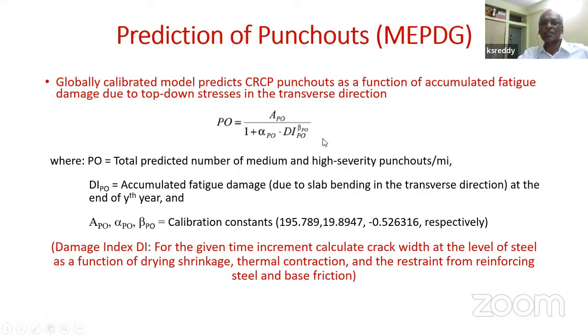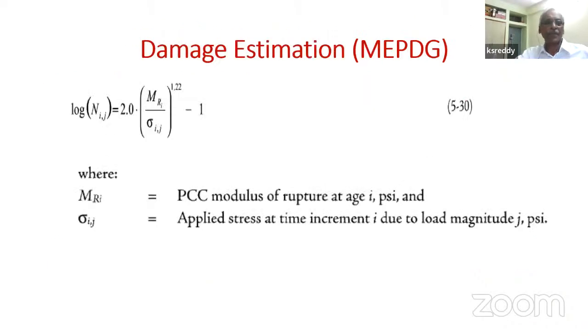These are the expressions that the Mechanistic-Empirical Pavement Design Guide uses to estimate how many punch outs will be there per mile in terms of cumulative fatigue damage estimation, which is similar to what we do in the Indian Roads Congress guidelines, IRC 58. You find out how many load repetitions, temperature gradients, calculate stresses, calculate cumulative fatigue damage during the design life period, and accordingly how the punch outs are going to increase, empirically correlated. They have developed correlations comparing the physically observed punch out numbers to the theoretically calculated damage index, basically cumulative fatigue damage.